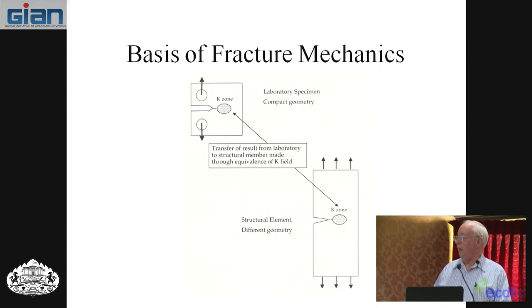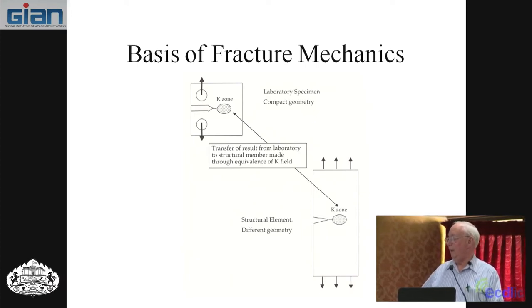So here is what you can do with the K approach. It's kind of the real basic fracture mechanics theory. You can go in the laboratory and use a specimen. A lot of our specimens look like this. In the laboratory, you use that specimen, and then if whatever fracture event happens to that specimen, you can relate that directly to the structure. And this is representative of a laboratory specimen. This is related to the structure itself. And this is the transfer term then. So the K and the K field is the transfer from laboratory to structure.